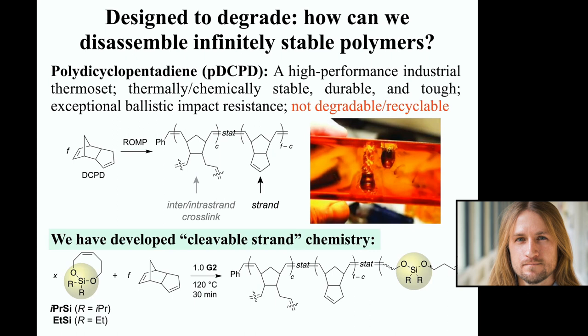And we know from prior work in the field of organic chemistry that these silicon-oxygen bonds can be selectively cleaved in the presence of different reagents, for example, fluoride ions, which are the key ingredient in your toothpaste. So we can use fluoride almost like a molecular scissors to go into this material and cut just those silicon-oxygen bonds. So the fundamental question we have is, what happens if we do that?